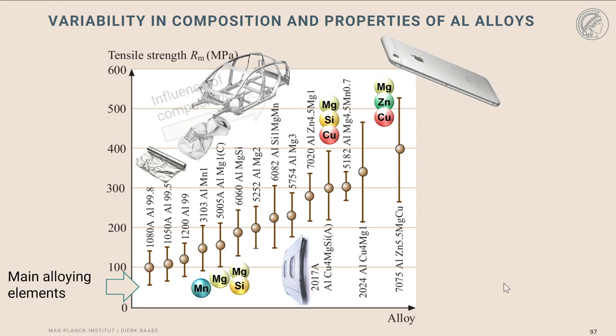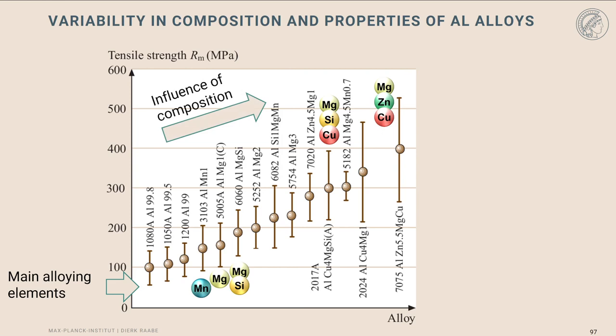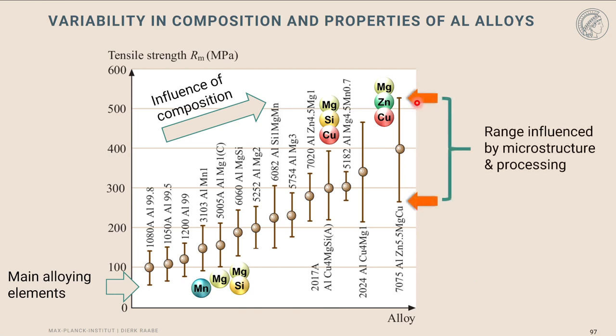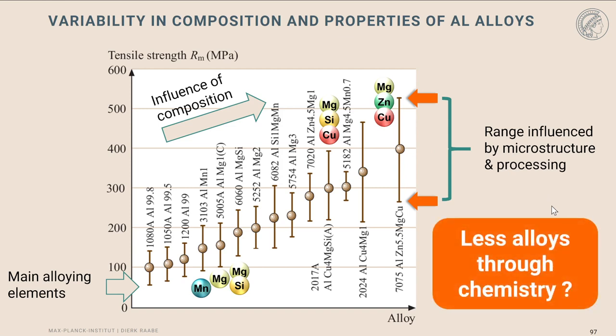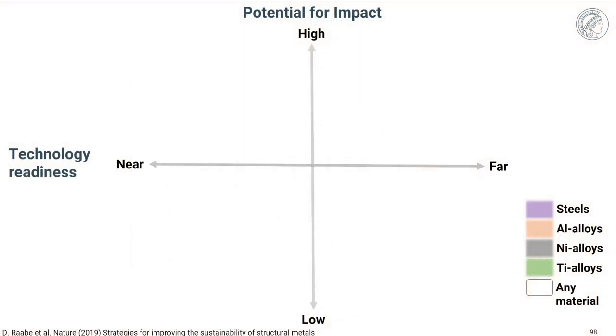devices. And on the one hand, we indeed see a certain clear trend that the tensile strength of these alloys increases with the overall aluminium alloying content. But on the other hand, you also realize that there's a huge scatter for each of these alloy groups. That means there's a big range for the tensile strength in this case that can obviously be influenced by microstructure and by processing. And that means in the future, we should maybe try really to design a higher variety of materials, not through chemical variants, but through microstructure variants.